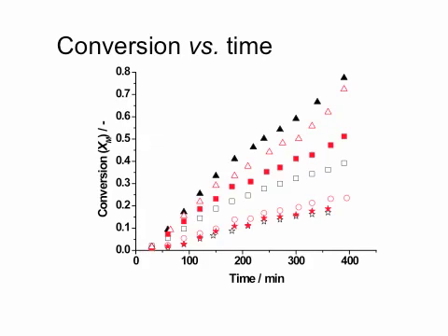If you go back to emulsion polymerization, we talked about different models, right? We talked about zero-one versus pseudo-bulk. Yeah, independent polymerization. So each particle can be considered as a reactor. What is the difference if I make my particle small? Exactly, radicals don't terminate. That effect is called compartmentalization. So the particles become smaller, compartmentalization kicks in, and the rate of polymerization becomes larger.